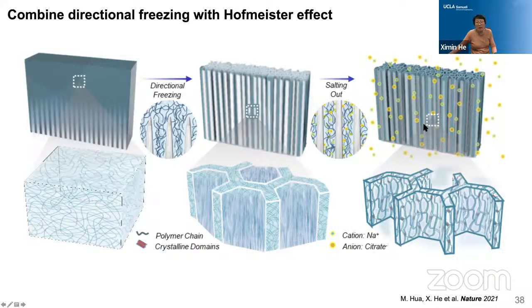So before we do this salt soaking treatment, we start with a polymer solution in water, and then we did this directional freezing first before the salt soaking. Here we utilize this directional freezing by placing the solution on a cold plate. This generated temperature gradient will produce the directional growth of ice crystals. Then in between the ice crystals, the polymer chains are pushed together, and they are closer to each other to be prepared for the subsequent salting out step. And then during the salt soaking, this induces the nanofibril structure formation on top of these microfibers formed from this freezing.